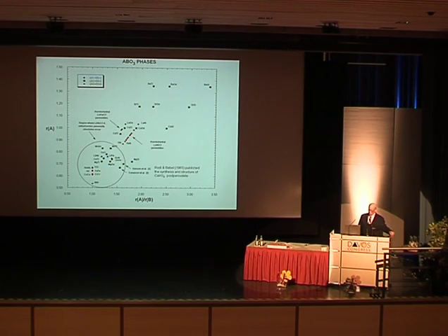Another application of the radii is to plot the radius of cation A versus the ratio of cation A to B. And this is a very useful way to show how the various compositions vary. And it turns out that, for example, the lanthanum aluminum oxide phases fall on lines such as this. And it's just very easy to characterize what's going on.